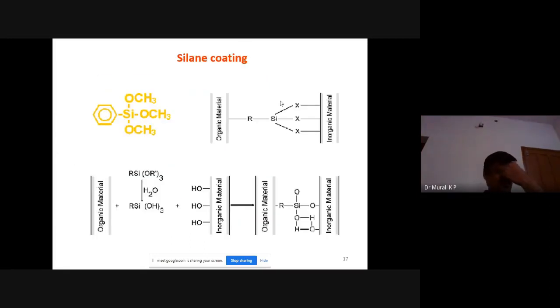And as you know, most of the ceramics are hydrophilic in nature. They have a tendency to absorb water. I have already told you the adverse effects if the material absorbs water: high loss tangent, low mechanical strength and all. So we have to preclude its hydrophilic nature. How can we do that? It is done by using silane coating.